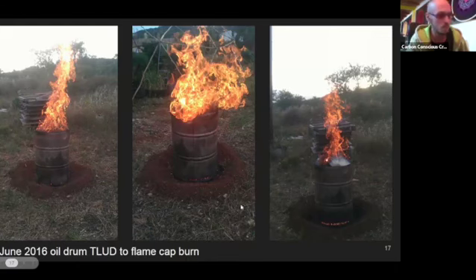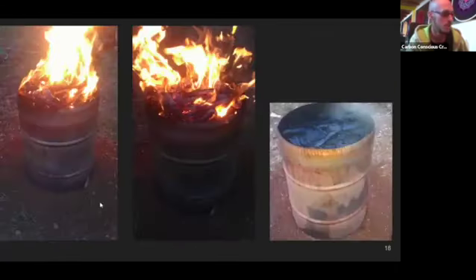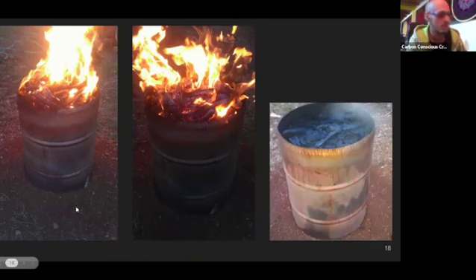And then as the burn progresses and as the barrel fills up with embers, I then close down the bottom air supply, and I just kept feeding it on the top as if it was a flame cap kiln until the barrel was completely full, at which point you can quench it with water, or alternatively, you can put a lid on top if you have a barrel that has a lid with a clamp. I have to say that personally, I prefer to water quench because I think it gives a better quality char. And you don't have the risk of opening things too soon, which can happen if you put a lid on it and you open it while it's still a bit hot, then it can just start smoldering again.